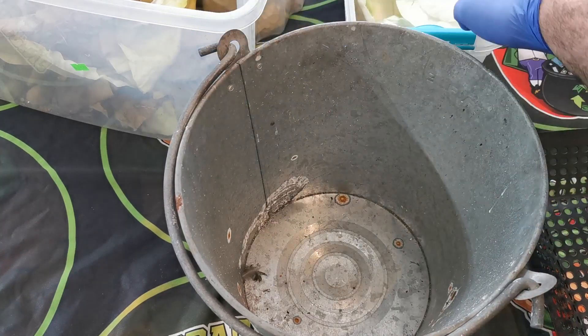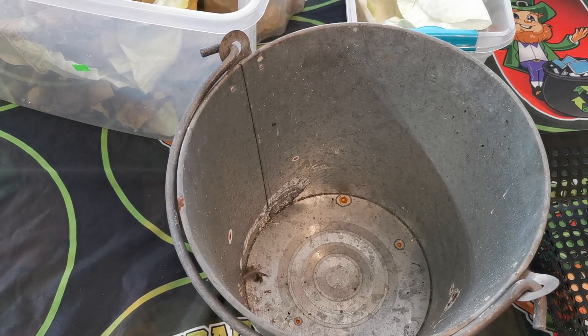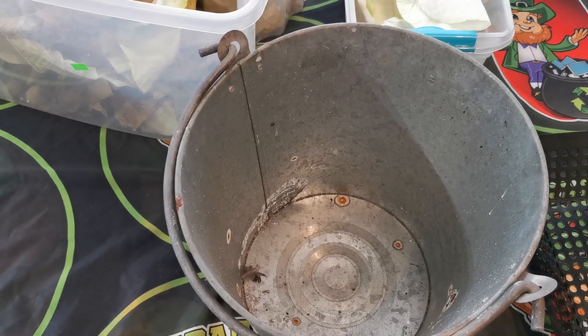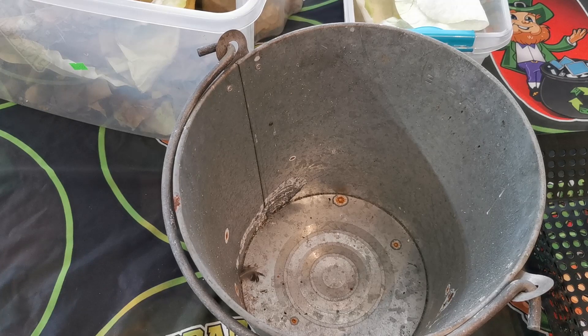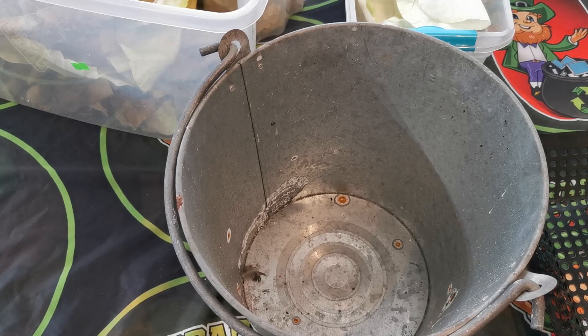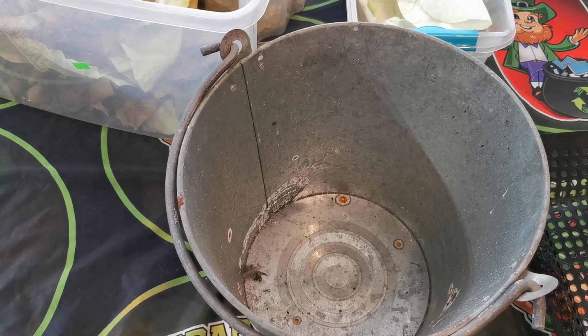I have a good amount of these — that tub over there, another tub here, and another one as well, built up over the last two years or so. My concern with putting them straight into aqua regia is that it uses a lot of liquid, and as the filters dissolve in the aqua regia, it goes gloopy and clogs it up. I think burning them first is the way to go.